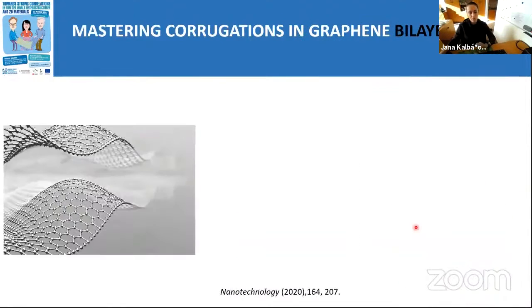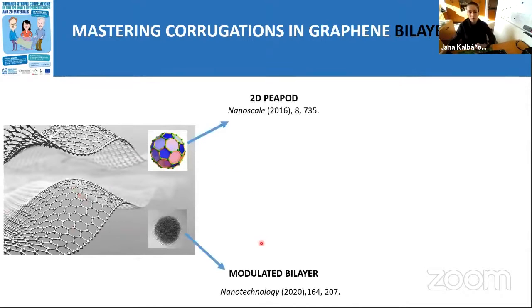So I would like to show you that in principle it's possible to apply a similar approach also for bilayer graphene. Instead of placing the sources of corrugation on a substrate, we can first put a graphene layer, then introduce again either fullerenes or particles on the bottom layer, and then on top we add another one. So you can imagine that we have a structure where there are areas where the two graphene layers stick together, so they are really in direct contact. However, there are some areas where the graphene layers are separated by either a particle or a pillar or whatever you can place in between the two layers.